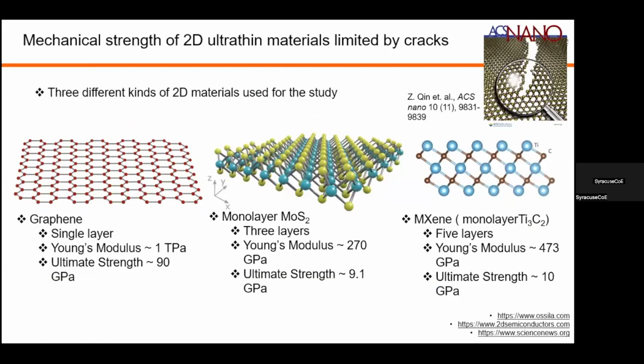So we switch gears to study the crack and failure of materials. This is a quick example showing how nanomaterials fail. The reason I picked that is that for nanomaterials, you have very clear visualization of how, atom by atom, a crack can propagate. If you check the frontier of the crack, those low-dimensional materials might give you the highest resolution to see the behavior of every single atom around the crack tip. These three typical two-dimensional materials are widely used in semiconductors: graphene, MoS2, and MXene. Current semiconductors still rely heavily on silicon, but for future development of semiconductors, people have repeatedly proposed using low-dimensional materials.